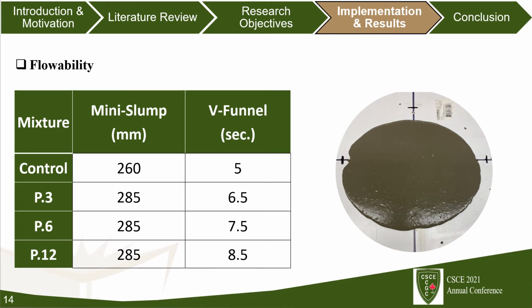For our results, we measured the flowability for our mix. All self-compacted mortars were in the recommended range between 250 and 300 millimeters. Besides, they maintained a flow time in the recommended range as well, between 2 and 10 seconds.